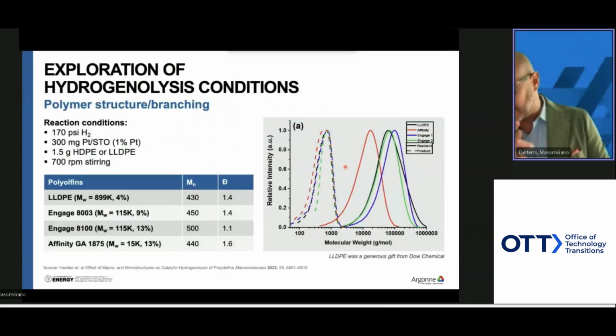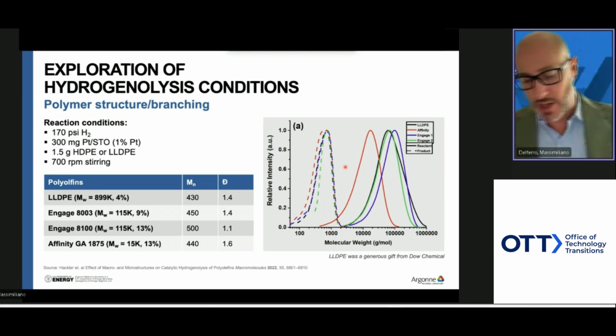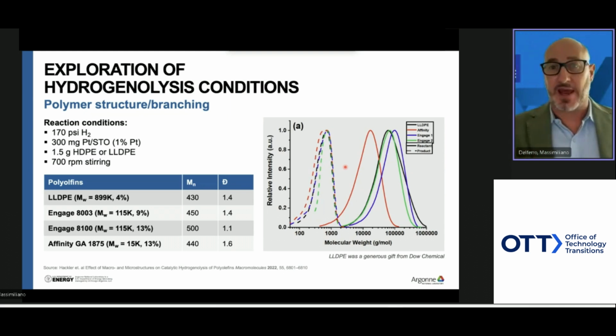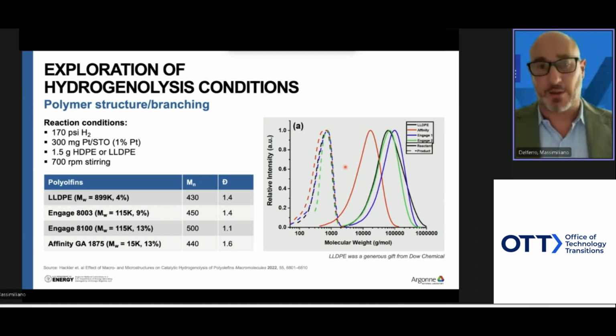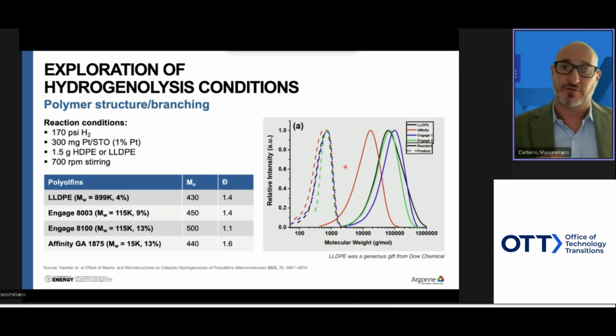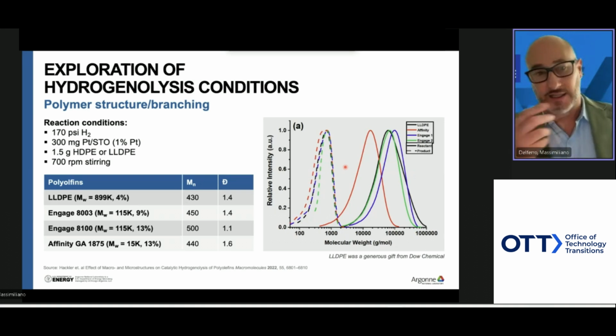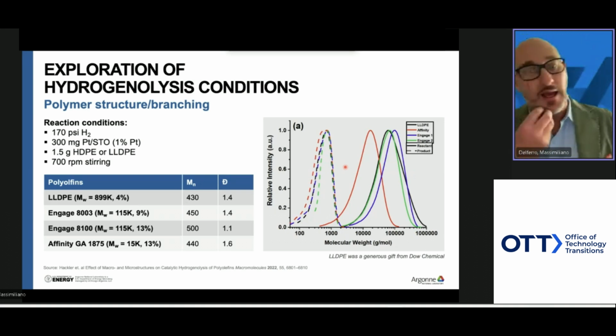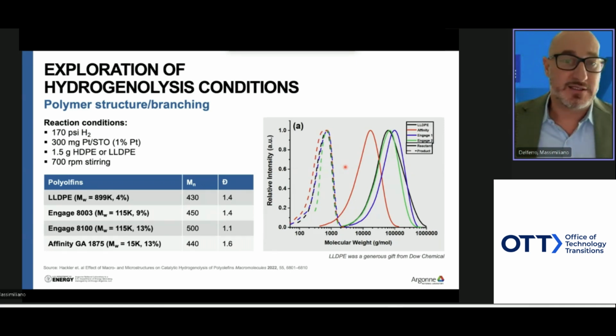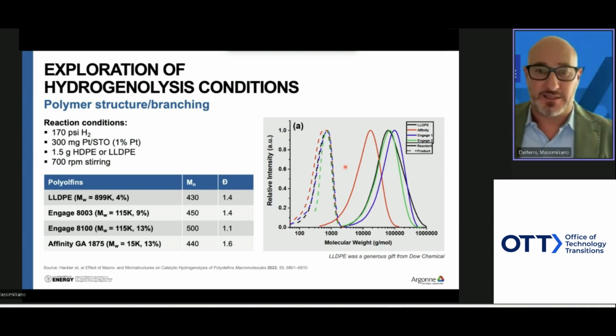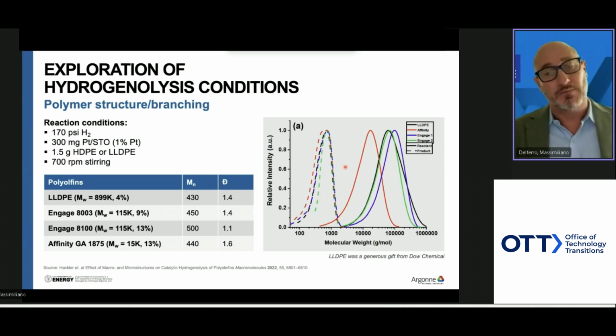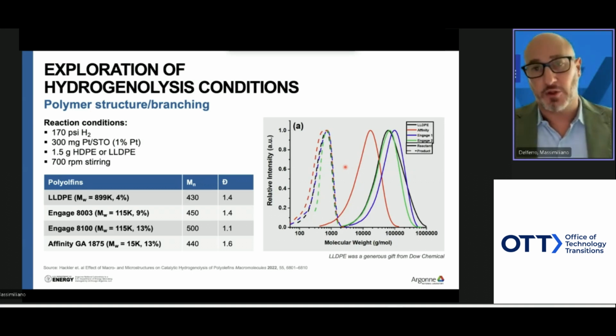As I mentioned before, the catalyst is really not targeting a single polymer, but we can, for example, produce liquids not just from high-density polyethylene, but also from other types of polymers. A classic example is linear low-density polyethylene. Most plastic bags are made of this material. And these are examples of real commercial polymer. There was a gift from Dow Chemical of linear low-density polyethylene with different molecular weights and different densities of branching. And as you can see in the table, under the same reaction conditions, the product that we obtain is independent of the molecular weight and the branch density.